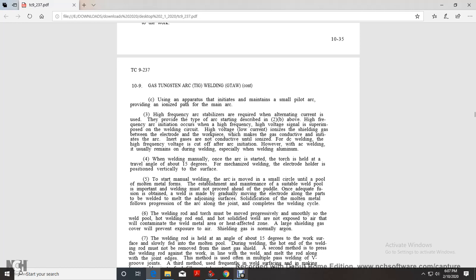Air and gases are not conductive until ionized. For DC welding, the high frequency voltage is cut off after arc initiation. However, in AC welding it usually remains during the welding, especially when welding aluminum. When welding manually, once the arc is started, the torch is held at a travel angle of 15 degrees. In mechanized welding, the electrode is held vertical to the surface.